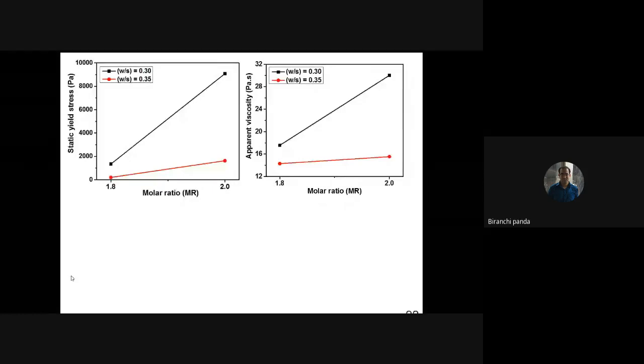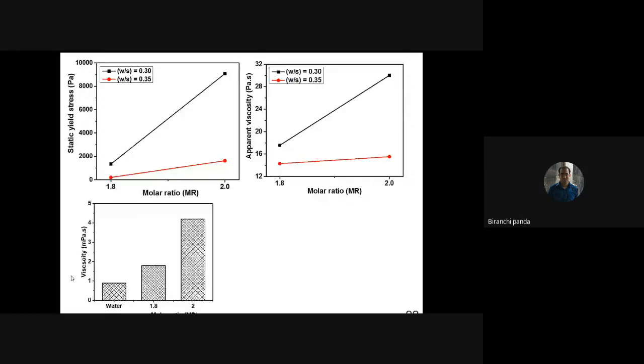And then we realized that the activator that we are using in our process is the main culprit, because the activator is available in different concentrations, or you can say different molar ratios. Different molar ratios of activator have different viscosity. As you can see in this picture, if you take 1.8, it has low viscosity. If you go for 2.0, it has high viscosity. So the activator viscosity is controlling the viscosity of my final material. As you can see in the top two pictures, different viscosity of the two materials has been recorded. When you use an activator of high concentration, you end up with a material of high viscosity. When the material viscosity is good, you can print a very well stable filament. But in the case of 1.8 molar ratio, since the viscosity was quite low, we can see that after extrusion, the layers are simply flowing away.